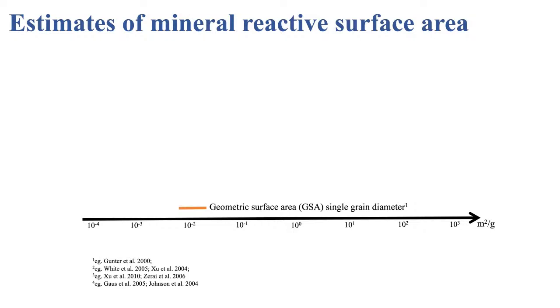The simplest approach is to use a geometric surface area where you just assume all minerals are perfectly smooth spheres of the same diameter. The problem with this, though, is that we know that clay minerals are inherently different than other minerals and have a much larger surface area. We can account for this by using two surface areas, one for clay minerals and one for everything else. But we also know that mineral surfaces are not perfectly smooth and have some amount of surface roughness. We can account for this by using a roughness factor. This is typically a factor of 10.